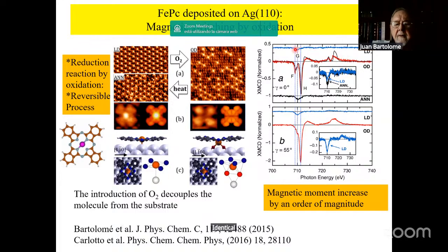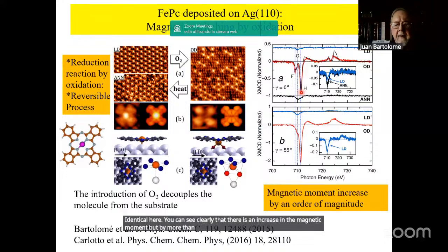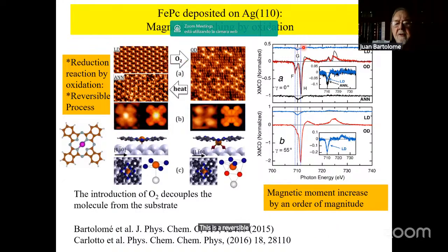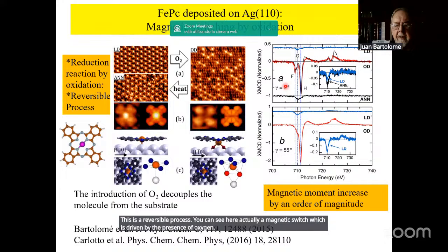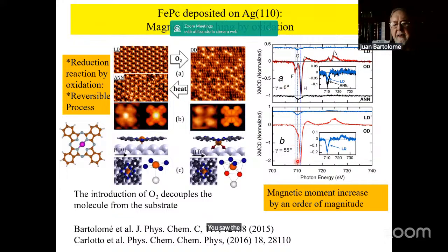You can see clearly that there is an increase in the magnetic moment, by more than an order of magnitude. What is also very curious is that when we take away the oxygen, we obtain back more or less the same magnetic state as at the beginning. So this is a reversible process. You can see here actually a magnetic switch, which is driven by the presence of oxygen. These are the angle dependence where we have seen exactly the same.